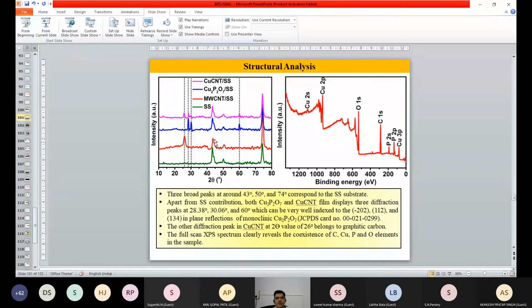Then this is the X-ray diffraction study for stainless steel with the carbon nanotube, then stainless steel with Cu2P2O7, and stainless steel which combines the carbon nanotube and Cu2P2O7, called CuCNT. And this is the XPS analysis, so that you can see the copper phase and P phase that is formed, and what the oxidation state is. So this is the full spectrum for this material which is developed on the carbon nanotube.